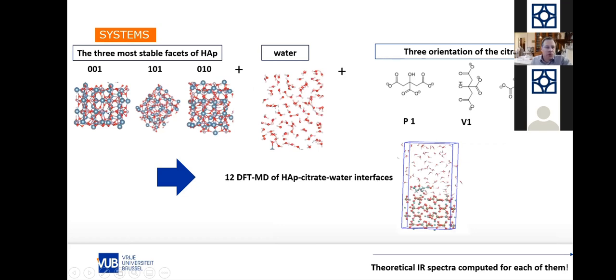The models again: we started with 3 orientations, 3 surfaces. We put water on it and equilibrated it. Then we put in 3 orientations of our citrate. We call them P1, V1, P2. I say that because you will see that in the structures later on. So this is typically the systems we calculate. It's all DFT here. CP2K was used for the calculation. So no force fields.